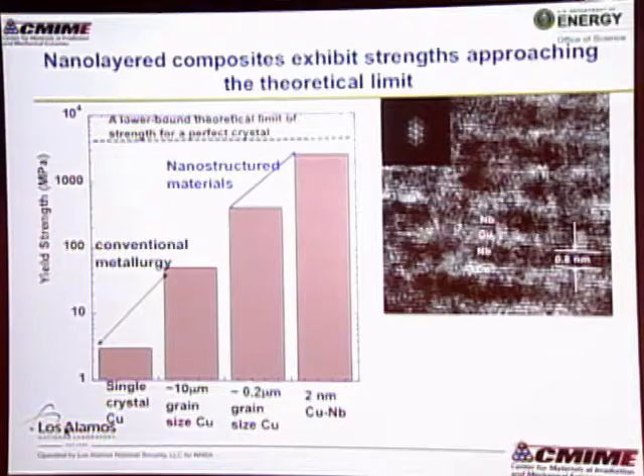If you start dropping that grain size within the material to 200 nanometers or 0.2 microns, you'll get a strength up here. If you start doing materials that are only 2 nanometers in layer thickness, in the case of copper niobium here, which there's actually a transmission electron micrograph here, just like Feynman was pushing for. In this case, you've got materials that are only about 5 or 6 atoms thick in each individual layer. The strength of this approaches that of what you would expect for a perfect crystal. So these are the types of materials that we're trying to make.